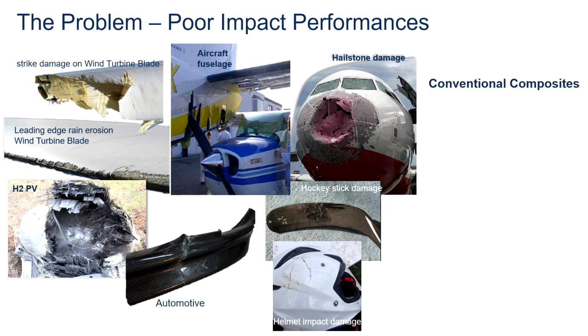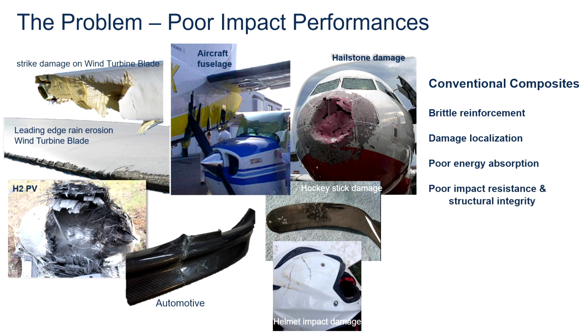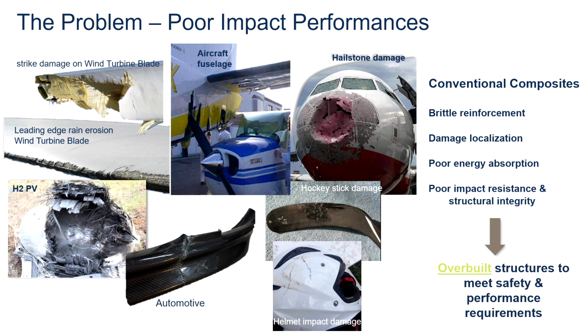So the reason for that is that in conventional composites, we tend to use brittle reinforcement. They tend to localize damage very easily. They have a poor energy absorption, and in turn, you achieve a very poor impact resistance and structural integrity. And as I mentioned, as a result, we overbuild the structure, right? We apply huge safety margins to avoid any type of damage occurring in the structure that could lead to a catastrophic type of failure.